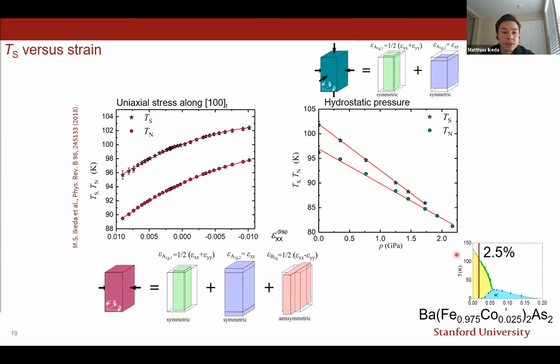The figure on the right-hand side shows our hydrostatic pressure data, and you can see that both phase transitions, the nematic as well as the antiferromagnetic phase transition, are tuned linearly with applied pressure. On the other hand, for our uniaxial stress experiment, we see a very pronounced nonlinearity. And since the strains that we induce through hydrostatic pressure in this experiment are significantly larger than the strains in our uniaxial stress experiment, we can conclude that the nonlinearity indeed stems from symmetry breaking B1g strain.